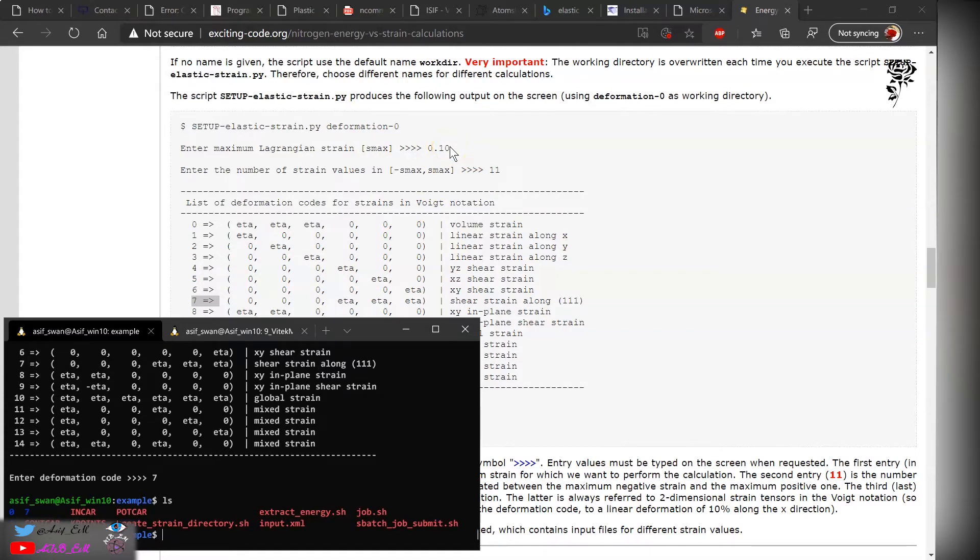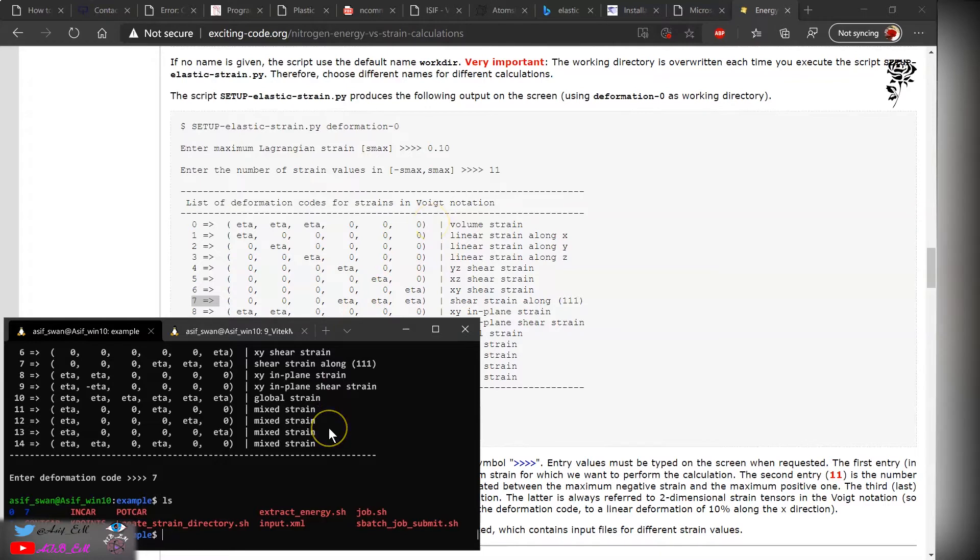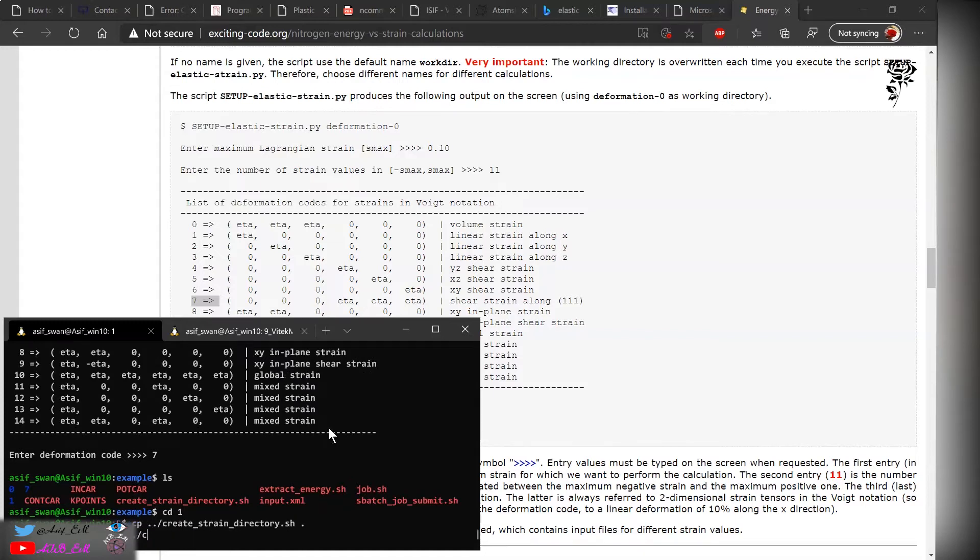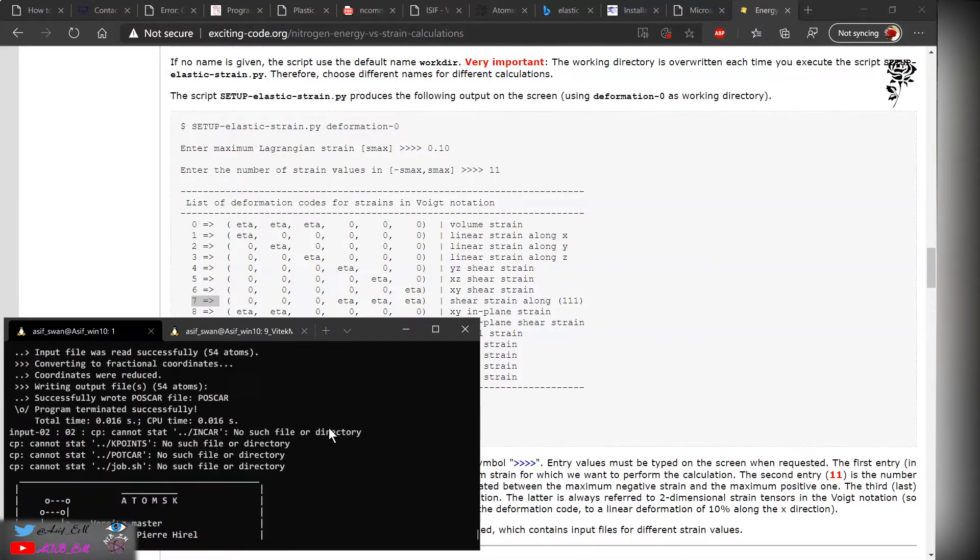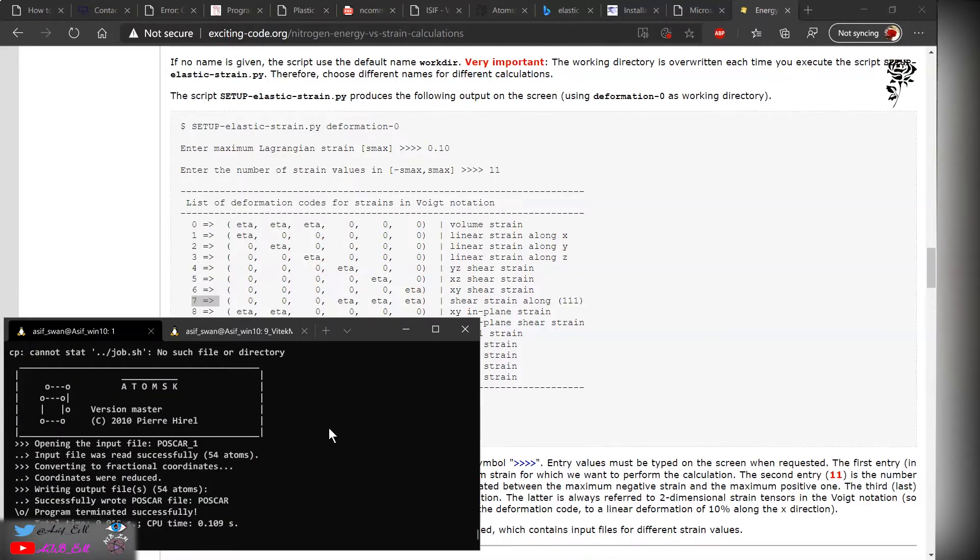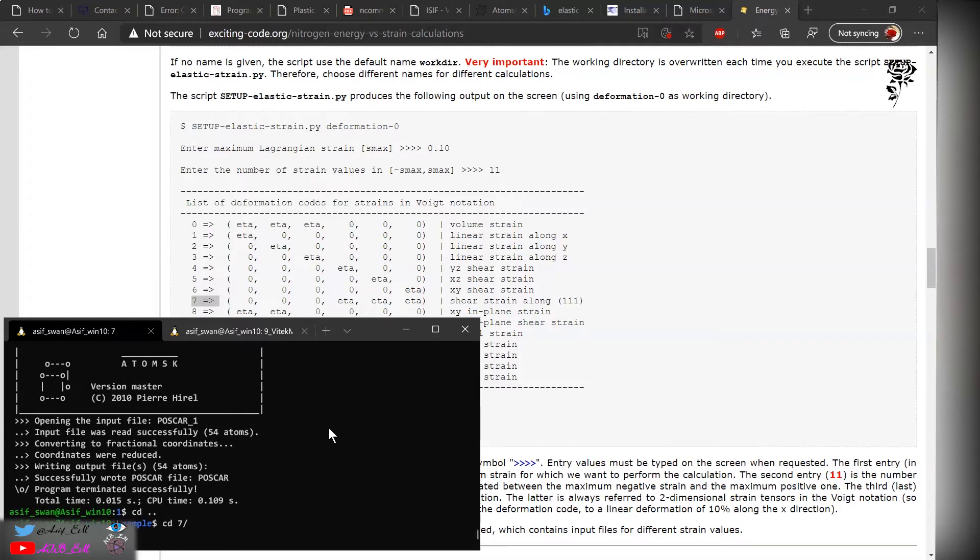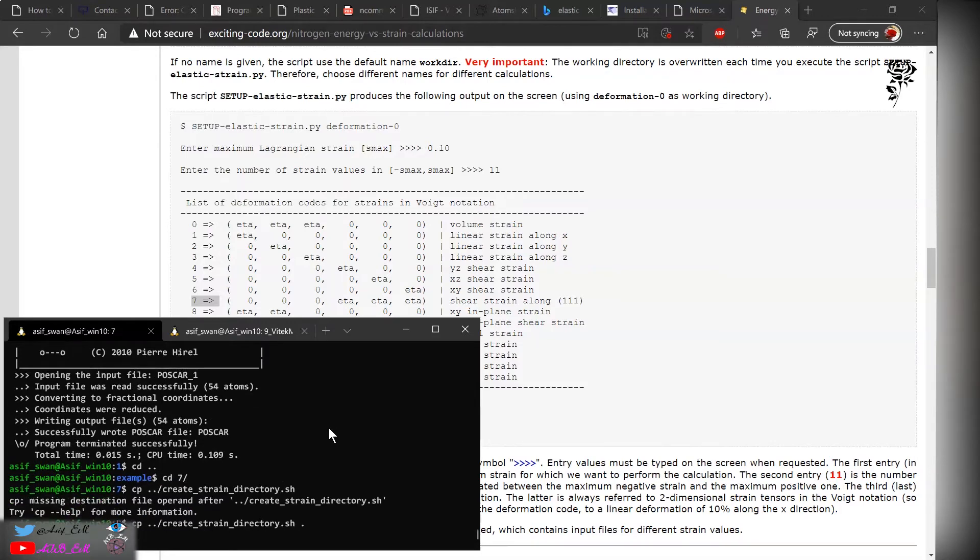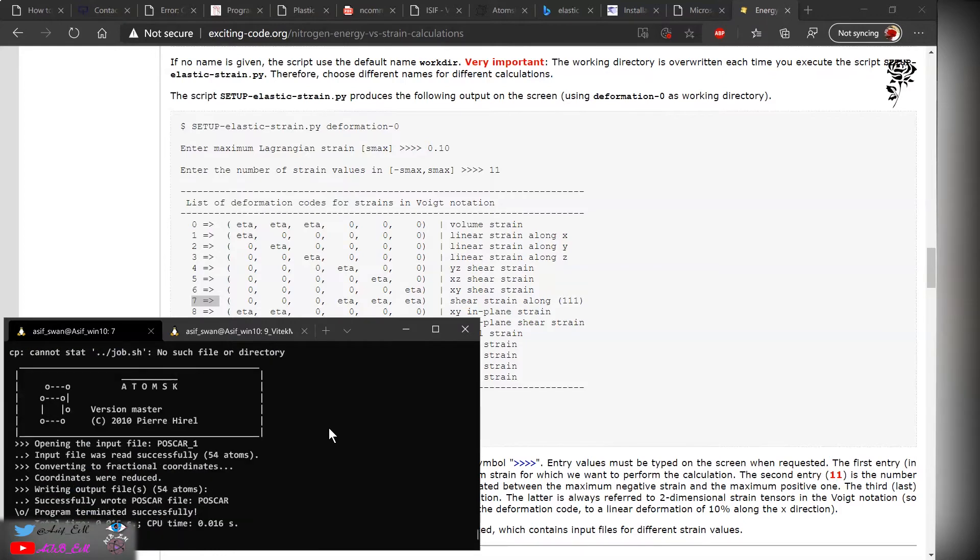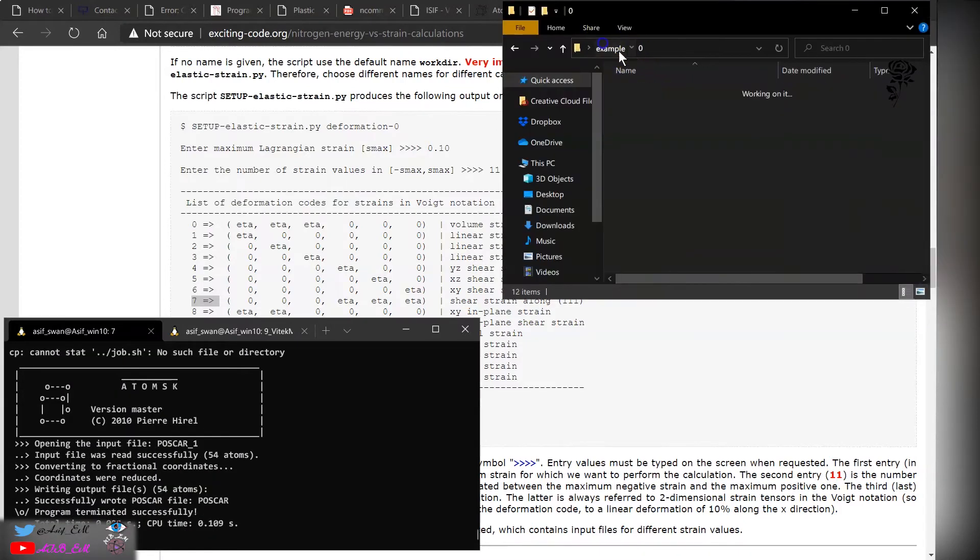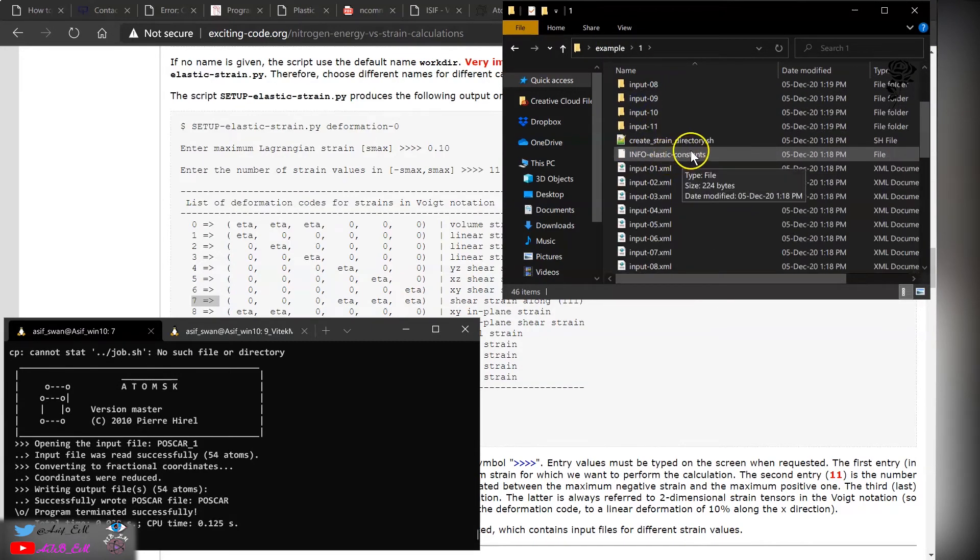Remember that the deformation in our case 0.1 could be large for high entropy, but you have to do by yourself convergence what is the appropriate value: 0.03, 0.05. This is for only demonstration purposes. Now we get into this folder again, and we create, and similarly for seven.